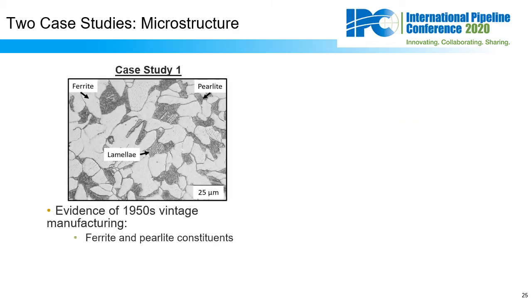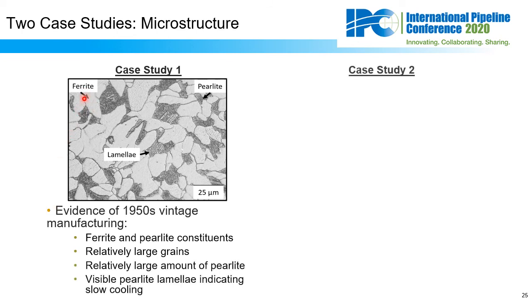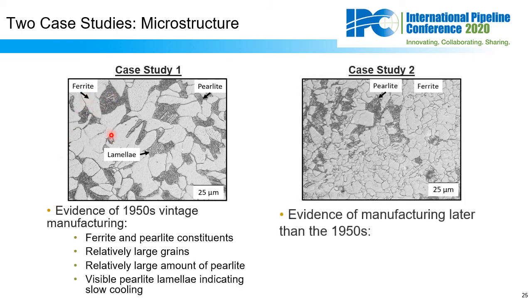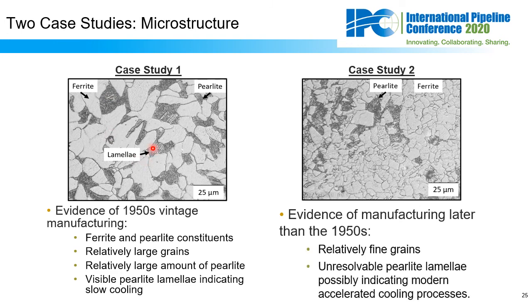Let's wrap up by examining the microstructure. For case study 1, we see relatively large ferrite grains and a good amount of this dark phase pearlite with these lines called lamella that indicate slow cooling. For case study 2, we see much finer ferrite grains and dark phase with no discernible lamella. So these provide evidence of manufacturing much later than the 1950s.